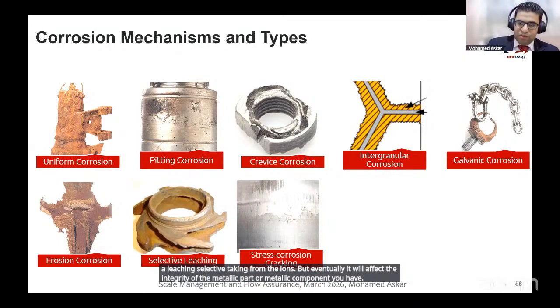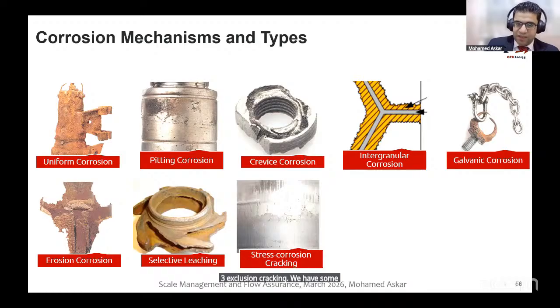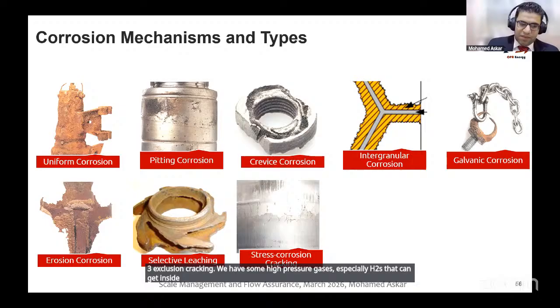Stress corrosion cracking: we have some high pressure gases, especially H2S, that can get inside the metallic parts and cause corrosion and cracking of these metallic components, especially for turbines, if you are using turbines with high pressure gases containing H2S.